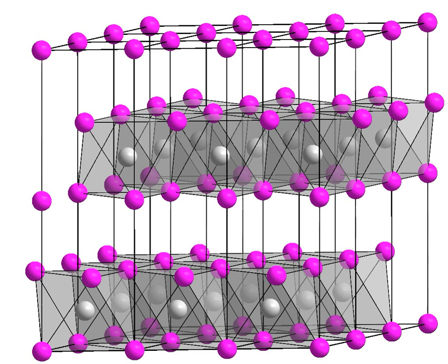Titanium disulfide also has the fastest rate of lithium-ion diffusion into the crystal lattice. The main problem was degradation of the cathode after multiple recycles. This reversible intercalation process allows the battery to be rechargeable. Additionally, titanium disulfide is the lightest and the cheapest of all group 4 and 5 layered dichalcogenides. In the 1990s, titanium disulfide was replaced by other cathode materials, manganese and cobalt oxides, in most rechargeable batteries.